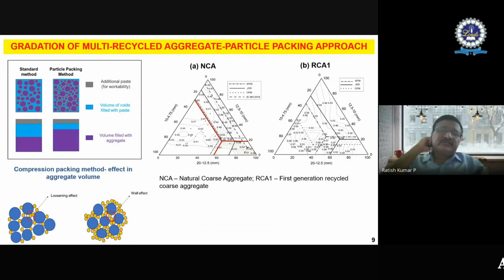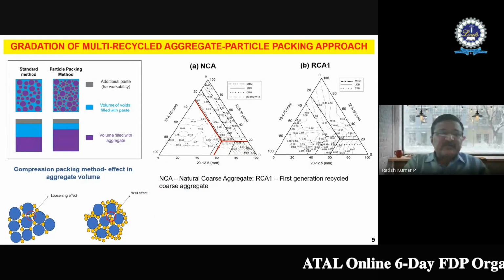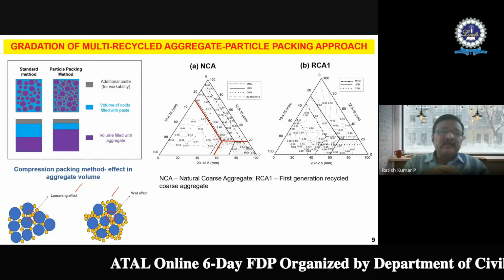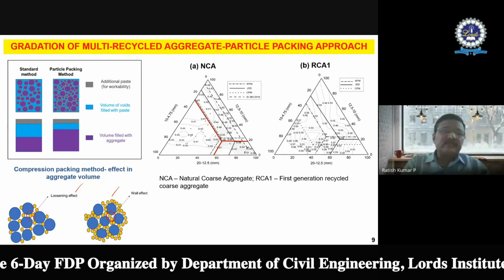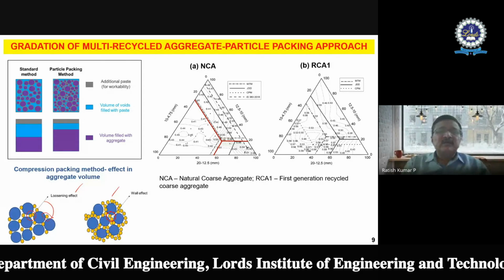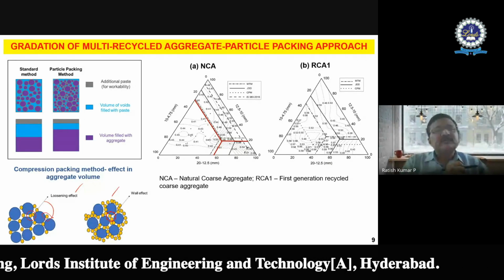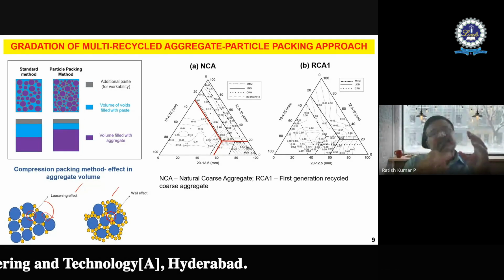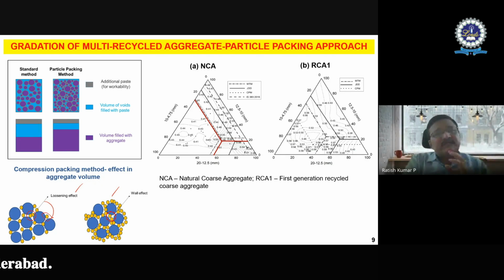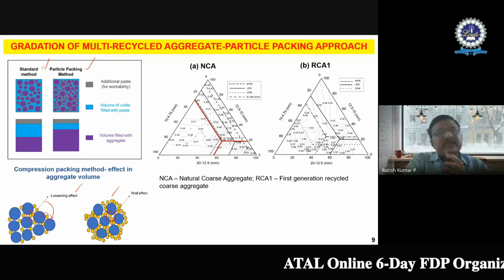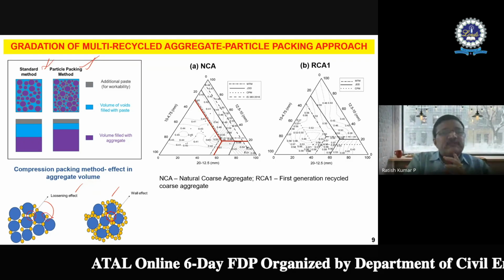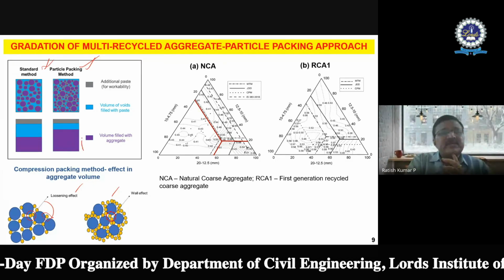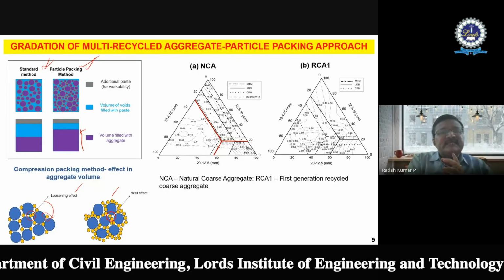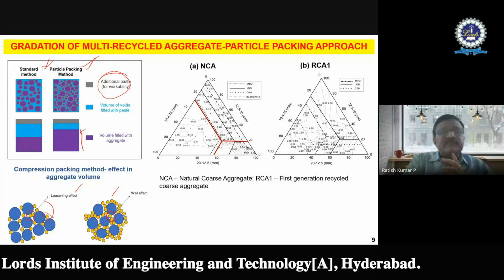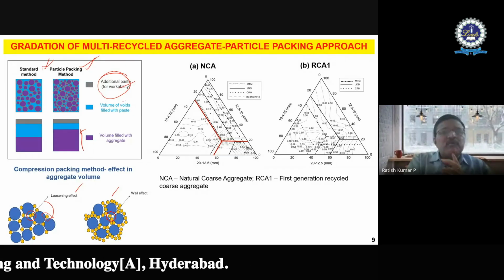Now, let me give you some idea about this. This is the loosening effect. These are the wall effects, where the bigger particles are fitting into the smaller particles, or the smaller particles are fitting into the bigger particles. We get a wall effect as well as a loosening effect. If I compare a standard method versus a particle packing method, you can notice my red ticks on the left and right side: the volume filled with aggregate is slightly increasing, and I'm leaving a lesser amount of additional paste. You can see the volume of voids is decreasing.